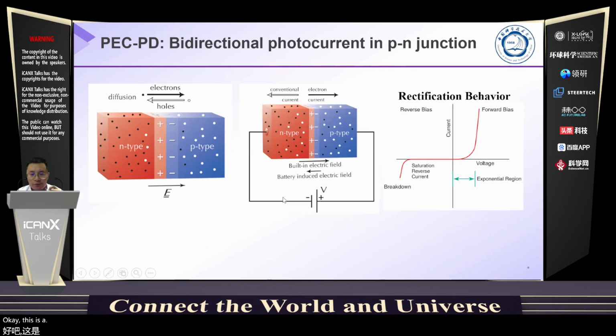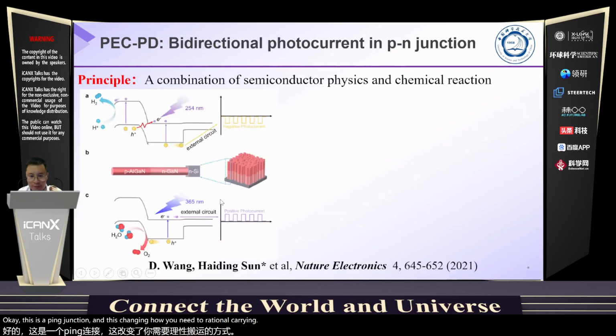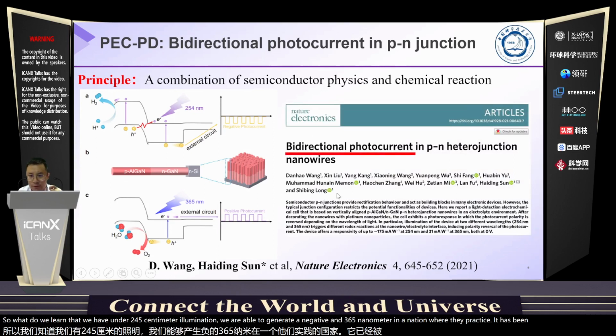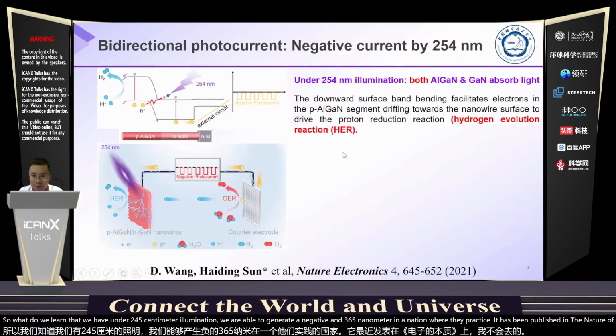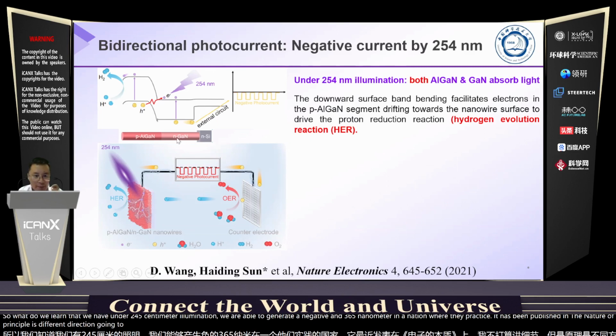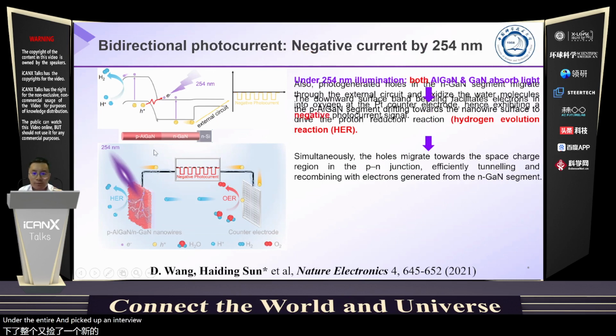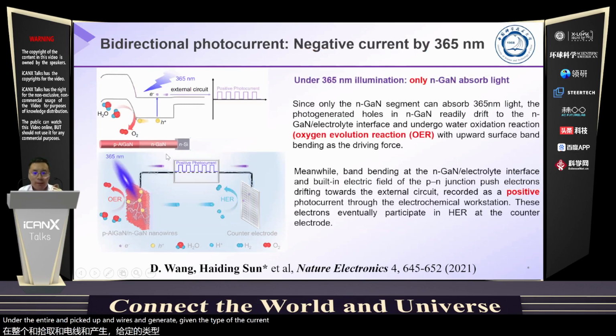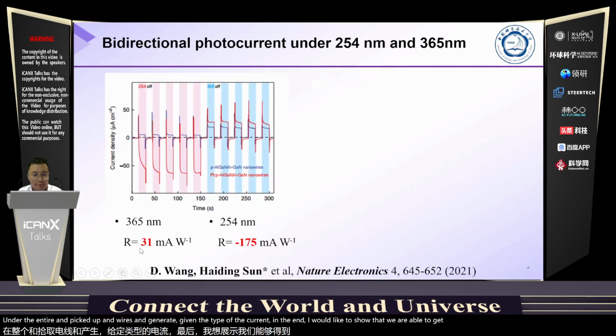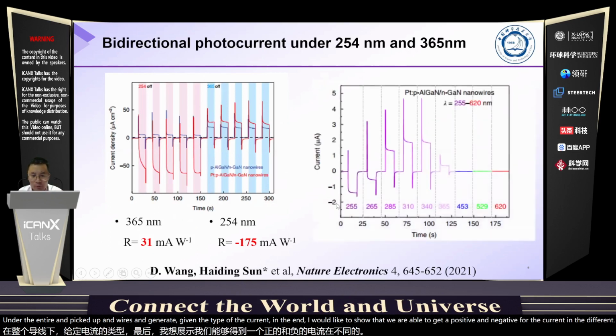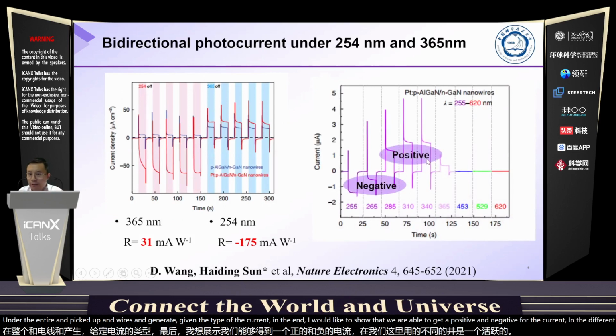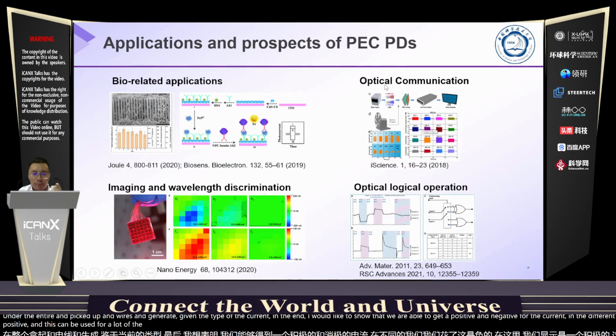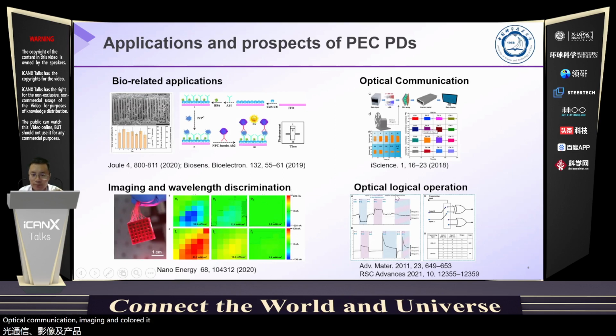This is a p-n junction, and this p-n junction has a bidirectional current. What we learned is that under 254 nanometer illumination, we are able to generate a negative photocurrent, and under 365 nanometer illumination, we get a positive photocurrent. This has been published in Nature Electronics recently, and I will not go into the details, but the principle is that different reactions happen on the N-type and the P-type nanowires, generating different types of photocurrent. In the end, I would like to show that we are able to get positive and negative photocurrent in different wavelength bands. Here we show the negative, and here we show the positive. This can be used for a lot of applications: bio, optical communication, imaging, color discrimination, and optical logic.